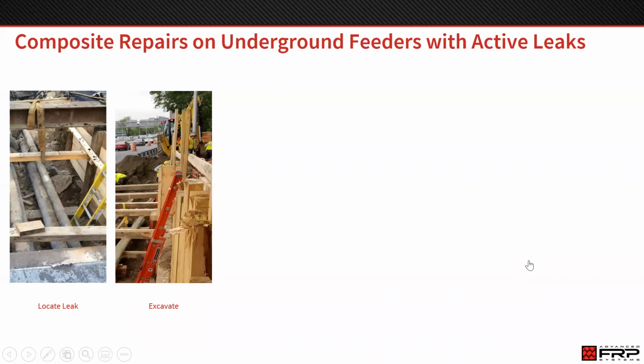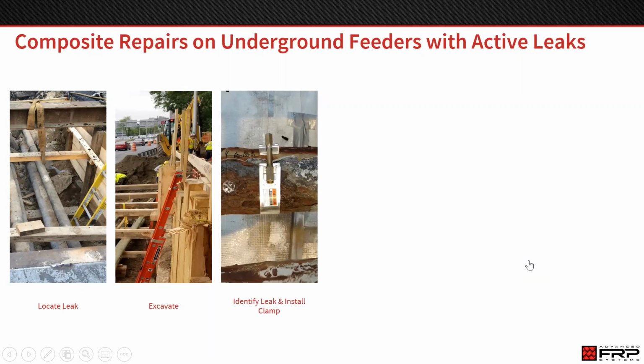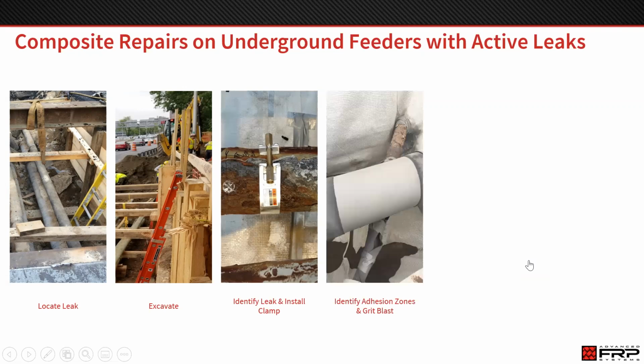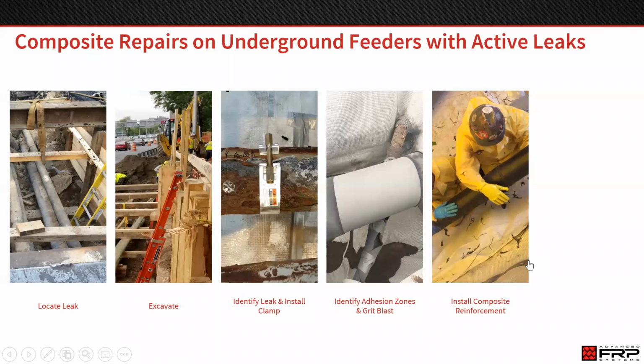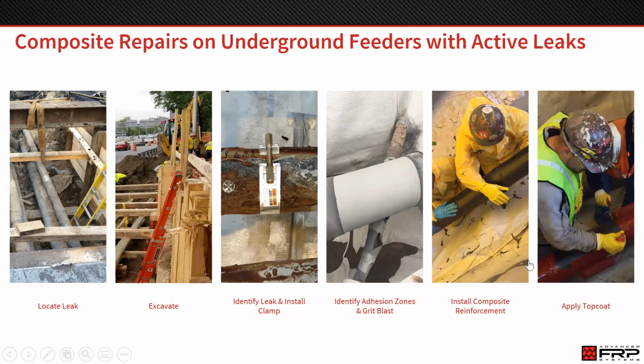All right, let's talk about a composite repair and exactly what it would look like. So in the same scenario with a leaking feeder line, the first 2 steps are the same. We locate the leak and we excavate. After that, we actually don't have to remove the existing coating. We just put a clamp on it or use another technique to stop the leak. After the leak is stopped, we will identify something called an adhesion zone, and we'll grit blast around on either side of the leak where the adhesion zone is, and that will allow us to wrap this pipe. Finally, we'll install the composite repair system and we'll apply a top coat.